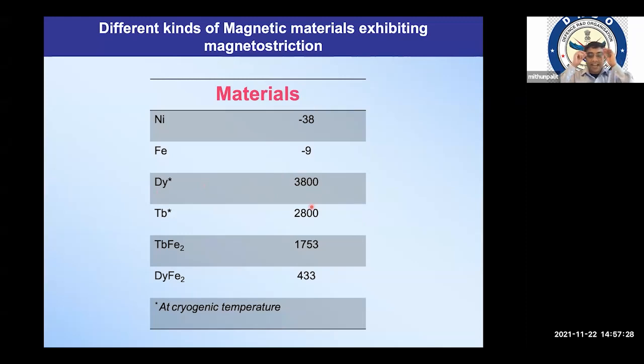So 3800 and 2800 parts per million. Whereas these two materials, you can see it is written here, are at cryogenic temperature. So therefore it cannot be used for any practical purpose. However, if we make an intermetallic combining a transition metal like nickel, iron, and a rare earth material like dysprosium and terbium, because they have very high magnetostriction and they have very high Curie temperature. So combining them, if we can make an intermetallic, we can realize a decent amount of strain which is operable at ambient or above ambient temperature.